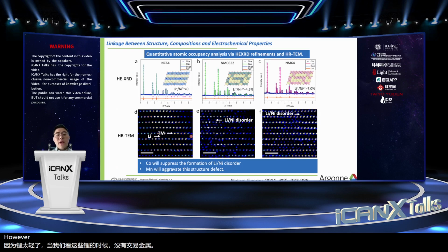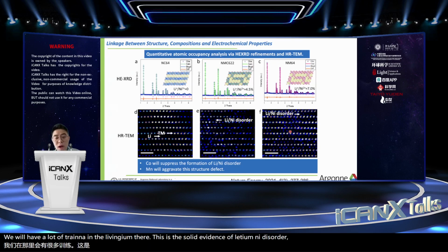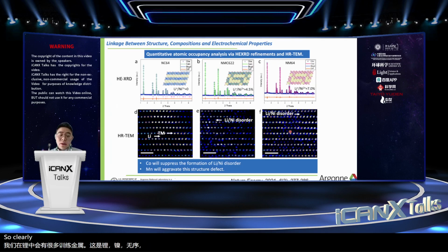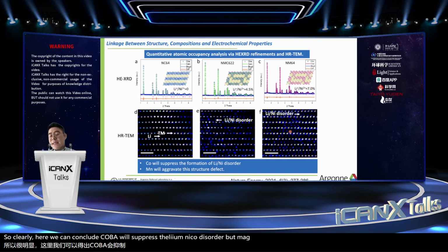However, when we remove cobalt or reduce cobalt to have the NMC622, we can start to see some transition metal in the lithium layer, and then when we completely remove the cobalt, we will have a lot of transition metal in the lithium layer. This is the solid evidence of lithium nickel disorder. So clearly, here we can conclude cobalt will suppress the lithium nickel disorder, but manganese will definitely increase the structure defects.